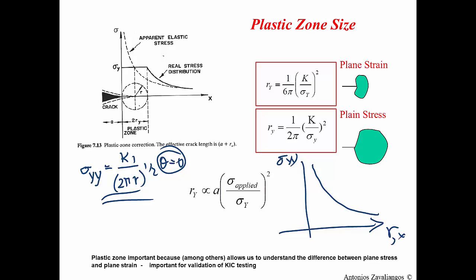And the easiest thing to do is actually say, okay, it is impossible for this stress to be going to infinity. There must be a limit. And what is that limit? That limit is actually the yield stress. And if you put the yield stress there, you can see that practically any material within this zone, and we can call this zone the plastic zone, is essentially plastically deforming.